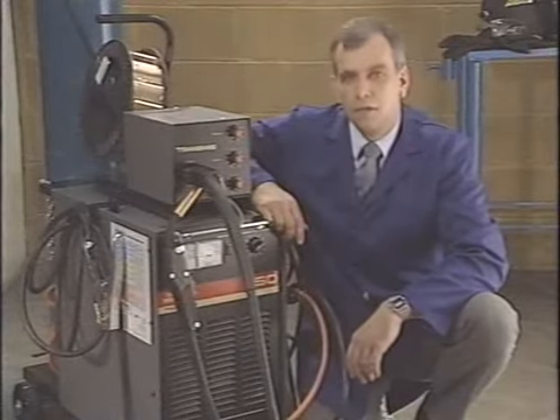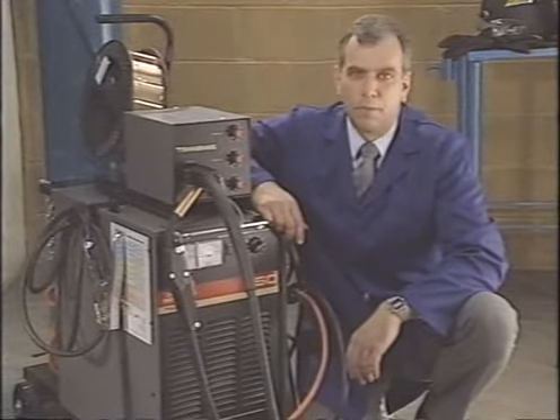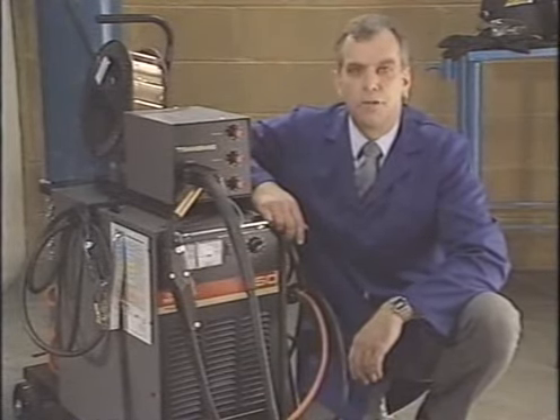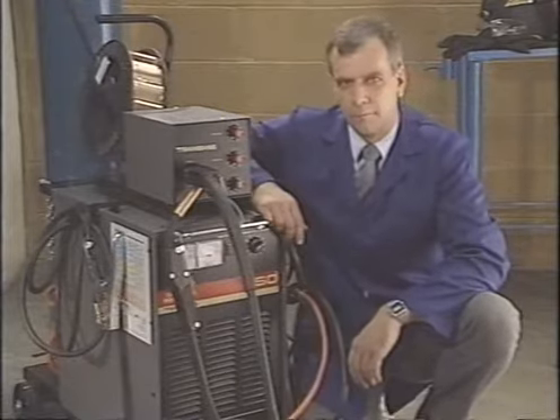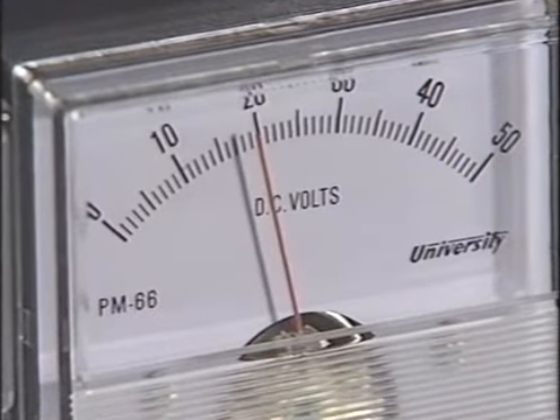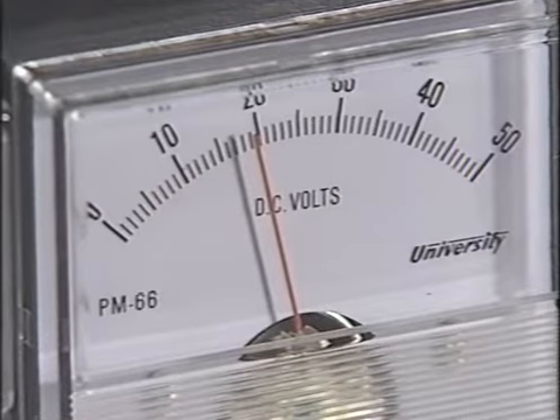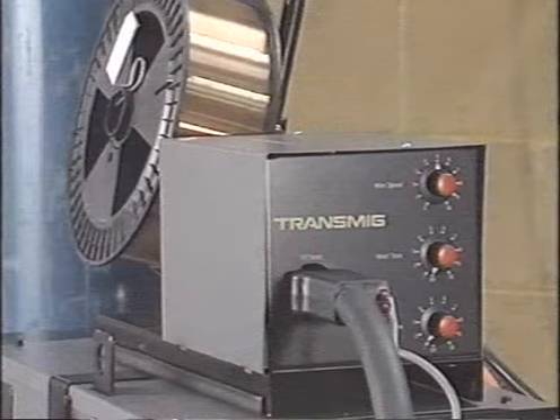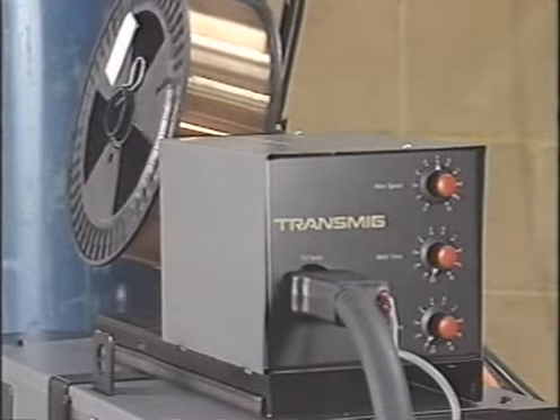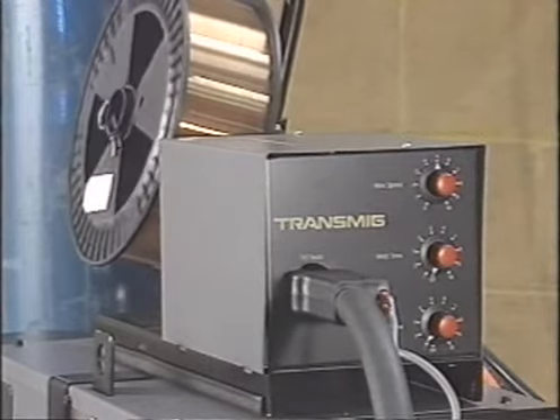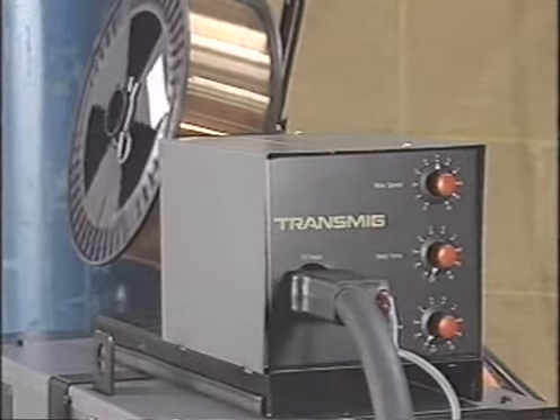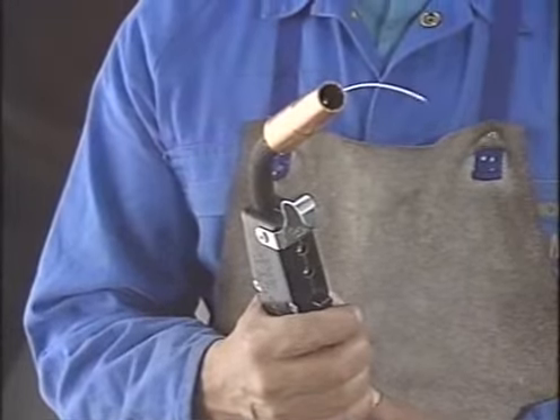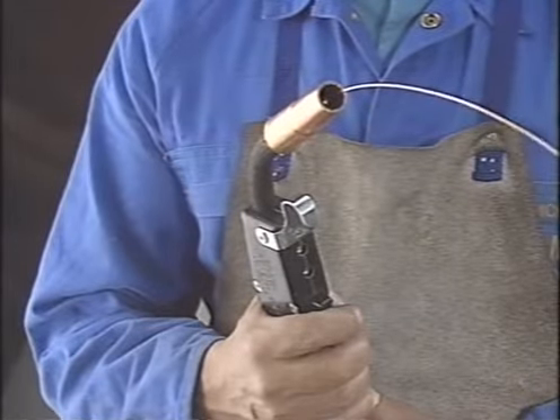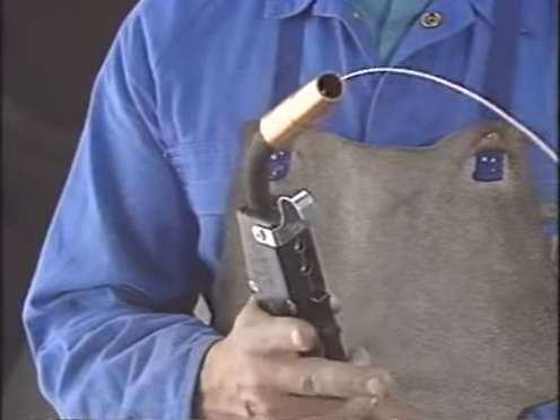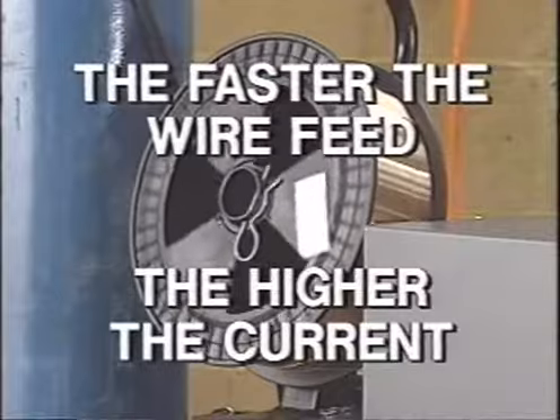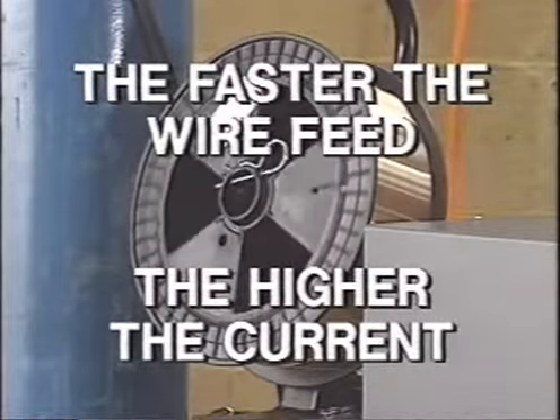A specially designed welding machine is used for MIG welding. The welding machine has a constant voltage power output. This means that the output voltage will remain consistent regardless of the welding current. A wire feed control unit enables the electrode wire to be fed as required from the spool. It is the rate at which the wire is fed through the torch which controls the welding current. Therefore, the faster the wire feed, the higher the welding current.